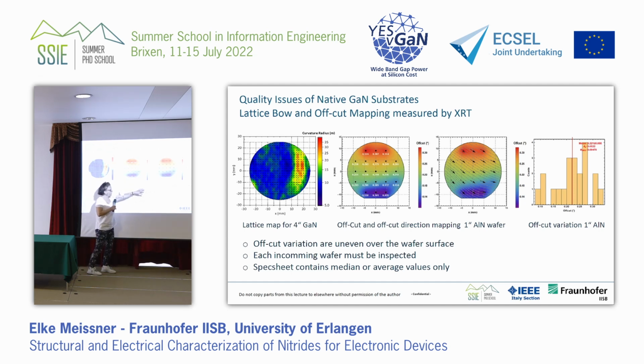The material is smaller, of course, but even if you have larger crystals like 2-inch, it's getting much, much better compared to gallium nitride. And you have offcuts which are on the order of 0.1 in the variation. Also the offcut direction counts, and you see even if you have large offcuts, they vary only between 0.1 and 0.3 maybe. So it's all not so severe in aluminum nitride like it's in gallium nitride, and this is also related to the growth method.